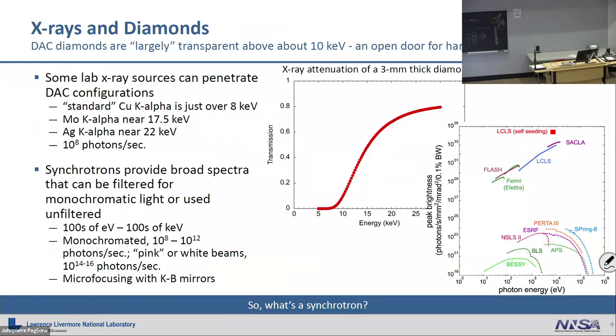So X-rays are not really good for looking at light elements. You can think about it if you have a lab X-ray source: you could probably measure alumina, it's probably okay. You can see some of the peaks from oxygen, but even aluminum nitride is going to start getting harder, and going down to something like aluminum boride is going to get really difficult to measure. So low energies can be difficult. The other problem in a DAC is that those low energies will get absorbed by the diamond. So it still absorbs X-rays, and that absorption also goes as the atomic number.